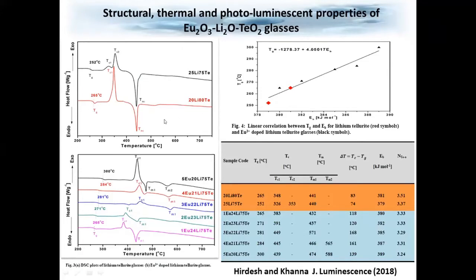So these are the thermal scans or the DSC patterns of the glasses. We see a glass transition at 265 degrees Celsius. These thermal analyses were done on a Setaram DSC system. This is for a lithium tellurite sample with 20 mole% of lithium oxide, and this is for a lithium tellurite sample with 25 mole%. And when you add europium ions from 1 to 2, 3, 4, 5, the glass transition temperature shifts towards higher temperature. So the network is becoming stronger. That is expected because the europium-oxygen bonding is very strong. The bond enthalpy of europium-oxygen is larger than that of the tellurium-oxygen bonding.